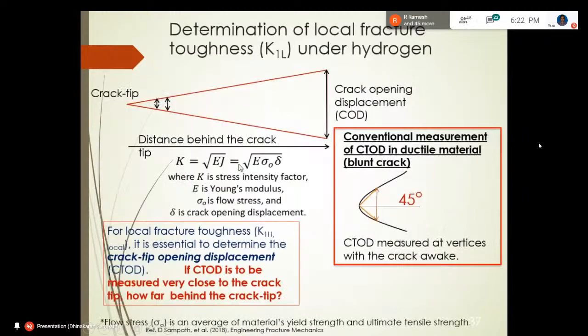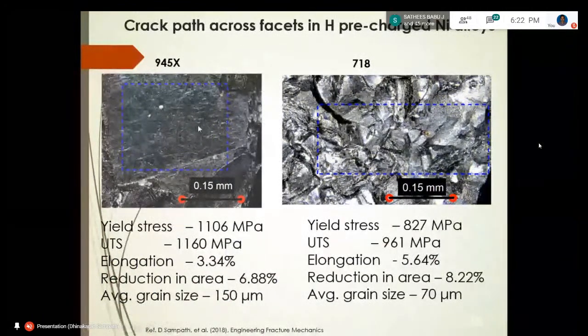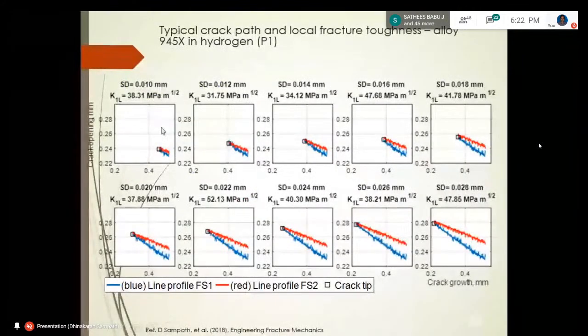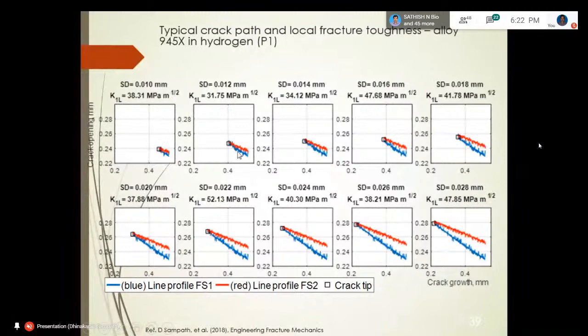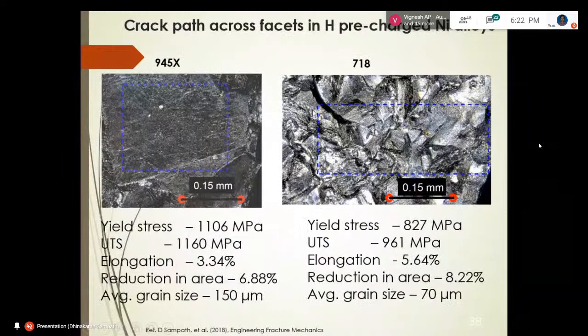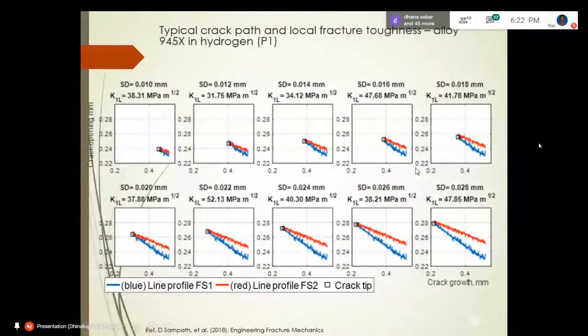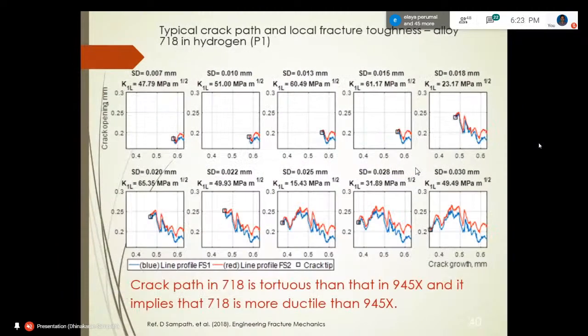So this is the formula. K is the square root of Young's modulus times flow stress times tip opening. We did that for 945x and 718. These are some details, and these are the cross sectional plots where we see that the crack is growing. This line analysis shows that the crack opening, one surface is moved with respect to the other, and also I plotted the local fracture toughness for each separation distance. When we did it for the entire surface area of 945x and 718, we get some kind of normal distribution. We'll see that in a minute.